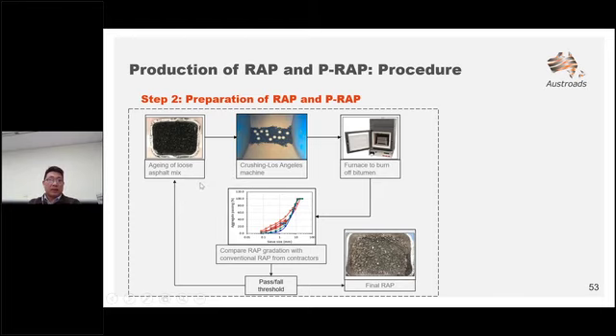Step 2 started when the aging procedure was finished, and the loose aged mix was crushed using the Los Angeles machine. Several trials were conducted with different revolutions using 12 steel balls for crushing of the loose mix. After each crushing trial, the binder was burned off in the furnace and the aggregate gradation was checked. If the RAP gradation passed the threshold, the crushing protocol was chosen, and then the RAP was used as the final RAP for the next step.